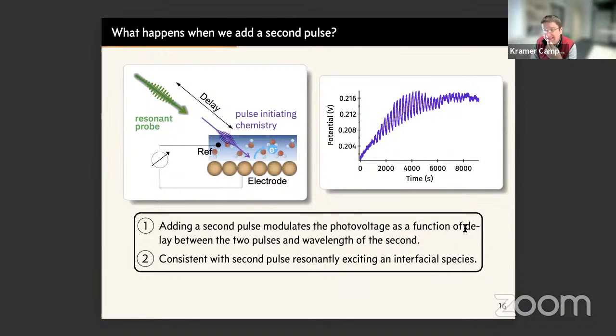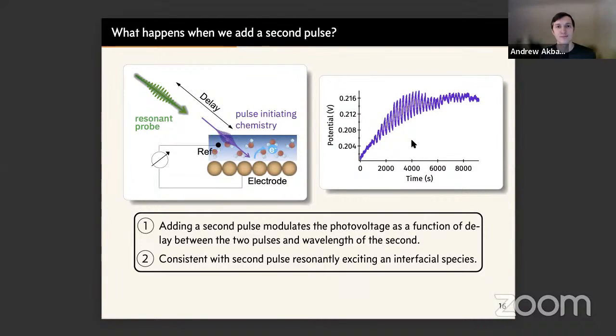So the pattern to the data reflects, as I said, maybe a note about this experiment. So this experiment is the dumbest, the most naive experiment possible. As I said, the laser runs at 1 kilohertz. So you have a femtosecond pulse every millisecond, and this potentiostat is just open. So there's something like a 12 order of magnitude mismatch between the sampling of the potentiostat and the laser excitation. So now we work on better detection schemes, trying to be somewhat smarter about this. So it was very surprising that this would work at all.